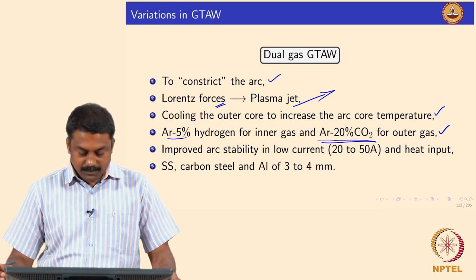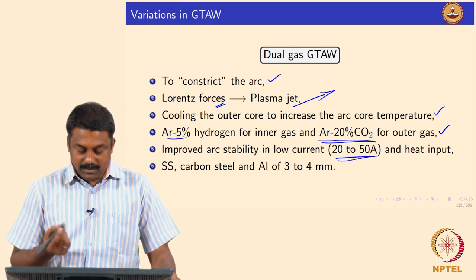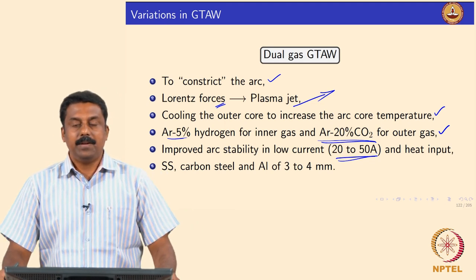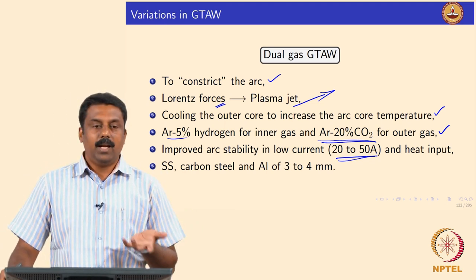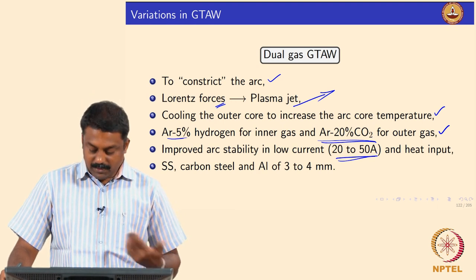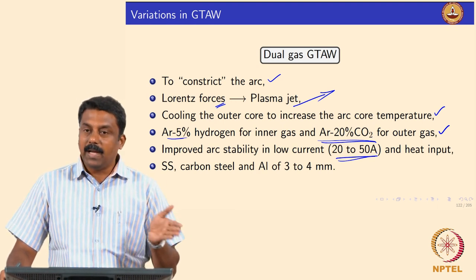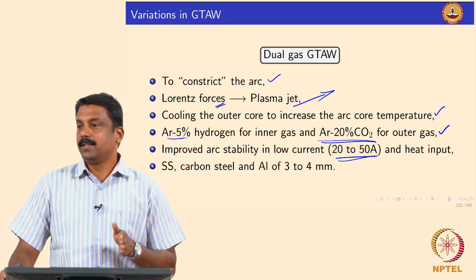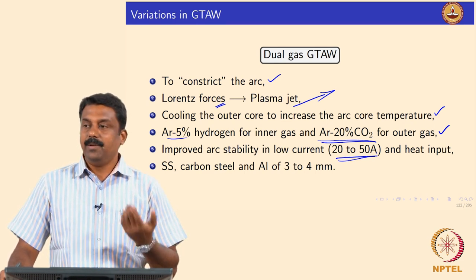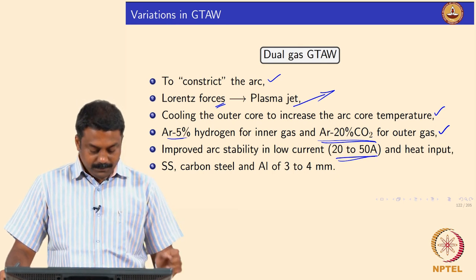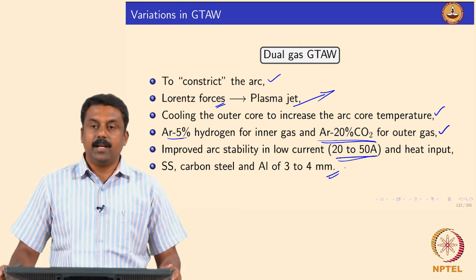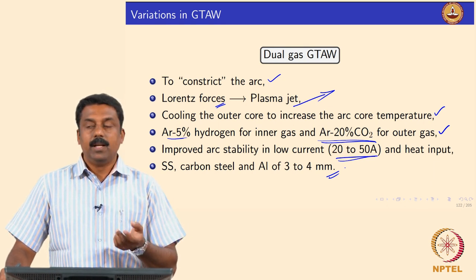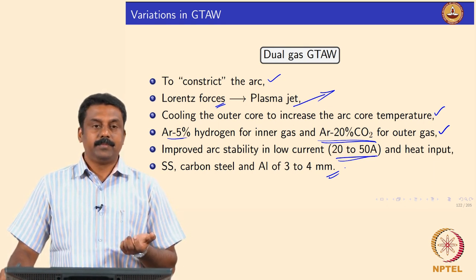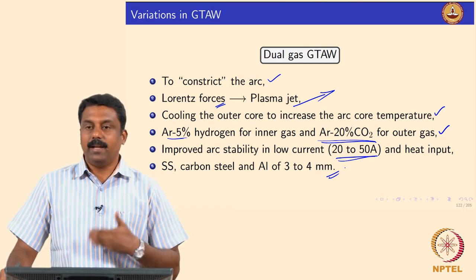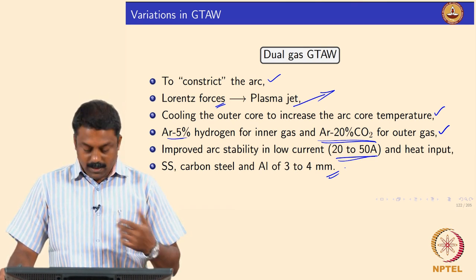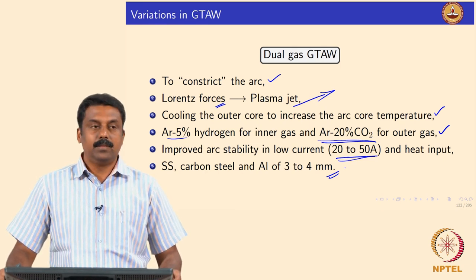So how does this work? Because of this modification, even with a very small current, we can generate a good amount of plasma. We will see in subsequent slides that even at microamperage, we can create a plasma. That is commonly used for welding of very thin sheets. And because of the increased plasma penetration, we can also get what is known as keyhole welding. Again, we will see in the subsequent slides that if you have very good penetration, we can also use it for keyhole welding.